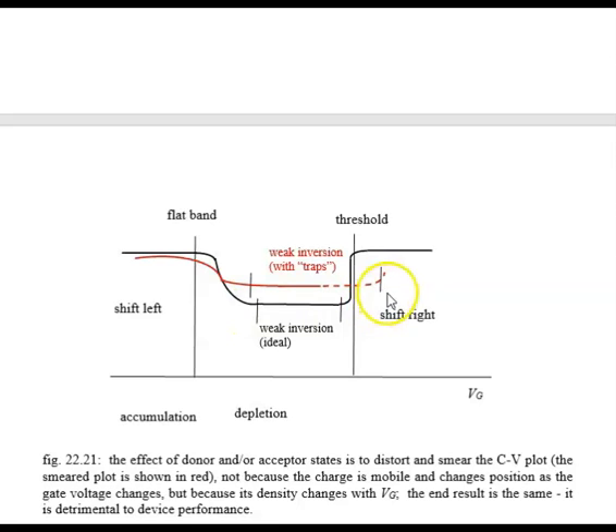If we do have interface traps, because the threshold is now shifted from this point to this point, the weak inversion region has stretched out, and that causes a very severe deterioration in the device performance. We see that on the CV plot, and we say, "Eek, that's not so good." Well, how do we deal with this in practice?